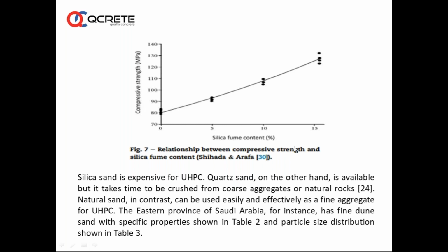And this also shows some research on the relationship between compressive strength and silica fume content. As the silica fume content goes up to 15% here, the compressive strength breaches the mark of 110, 120, which is required for UHPC. That is why silica fume has almost become an integral part of UHPC.